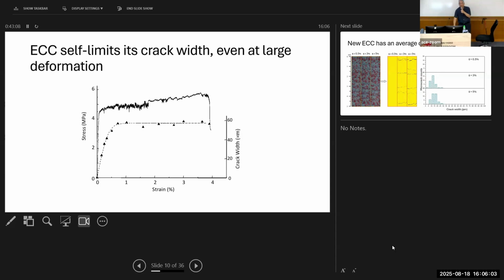So how large is 60 microns? Can anybody tell me the size of our human hair? What's the diameter roughly on average speaking? How many? Several micron. Okay, any other guess? 10 to 20? Okay, I believe there are human beings with those very, very fine hair. But typically on average, it's about 100 micron. So 60 micron is roughly about half the size of human hair, right? So it's very thin cracks, truly hairline cracks. And what is remarkable is that these cracks maintain their width. They don't open up anymore, even when you strain it to several percent strain.